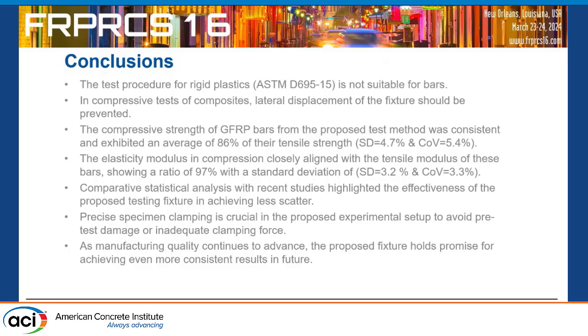With that being said, I would like to conclude this presentation. So it's obvious that ASTM D695 is not appropriate for testing GFRP bars. A new test method, a fixture, is needed for that. So we developed a new test fixture. We got the concept from the flat FRPs and converted it to compression. In terms of compressive strength, 86%. In terms of modulus of elasticity, 97% of the tensile one.